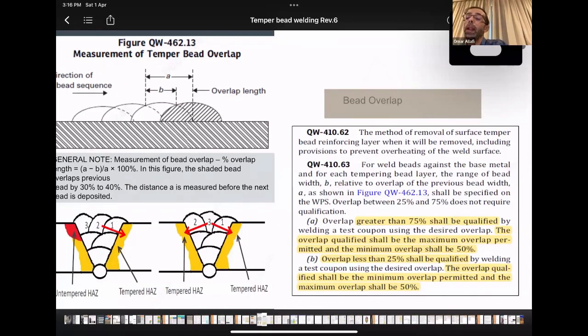what should you do now? Let's say that I want to have an overlap of 80%. So now you have to make an overlap of 80% in the test coupon, but that will change the minimum overlap. So it will not be within the range of 25 to 75. Now your new overlap value, which is 80, is the maximum, and the minimum is 50.